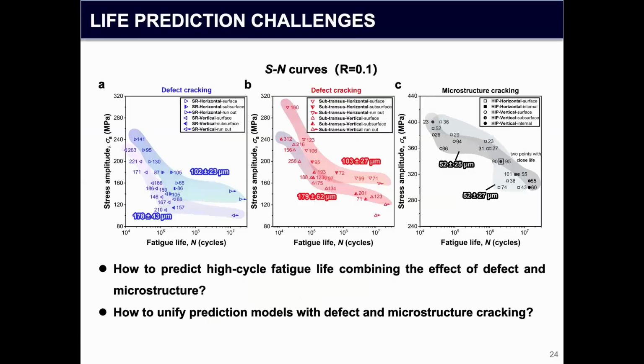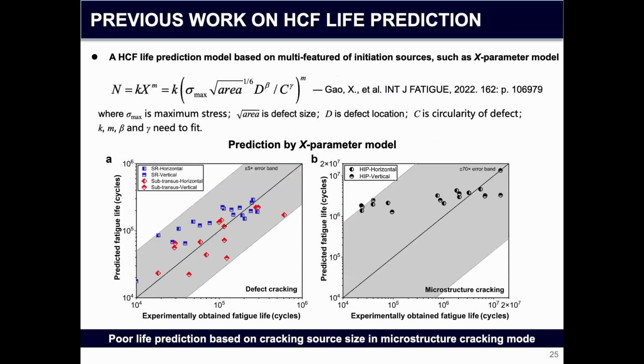So the last thing is about the life prediction. Actually, we would like to solve these 2 challenges. Okay, I will be quick. We already have some models in the literature, for example, the X-parameter model. But unfortunately, when we use this model for our material, we get a very poor life prediction based on cracking source size in the microstructure cracking mode. For example, the error bounds can be as high as 70 times.